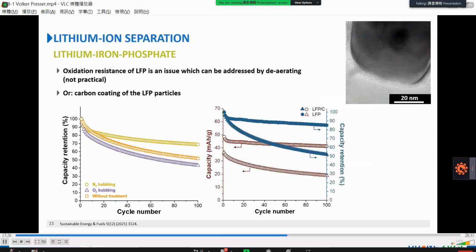A more practical approach was demonstrated by us: applying a carbon coating around the LFP particles also gives very stable performance and higher capacity retention over continuous cycling, specifically for lithium extraction.